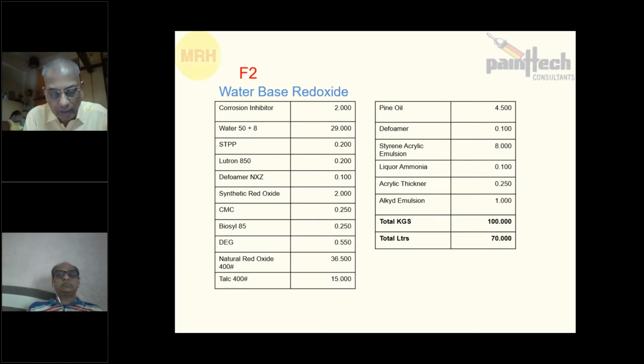I will get hotbox stability for 1 year, and hotbox stability for 3 to 5 to 7 days. Salt spray around 300 hours, 250 to 300 hours.